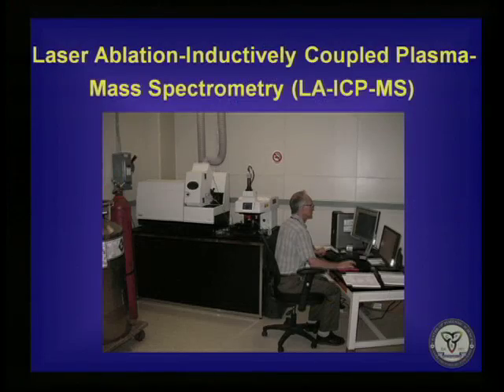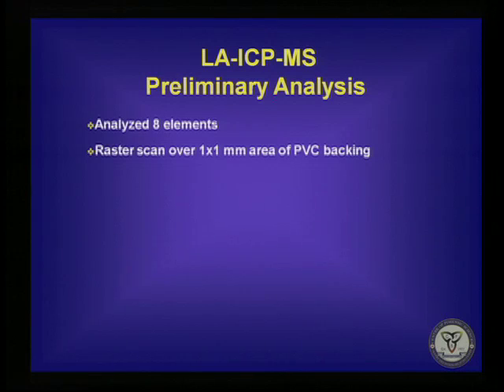So I'm going to spend the last bit of my talk talking about the elemental composition from laser ablation inductively coupled plasma mass spectrometry. This is a technique that allows the determination of elemental composition at the ppm levels of multiple elements. And again, this is preliminary work that we've done. We analyzed 8 elements, and for 2 of those elements, lead and antimony, we looked at 2 isotopes. We did a raster scan over a 1 by 1 millimeter area of the PVC backing. And for our preliminary data analysis, we used a criteria of plus or minus 40%.